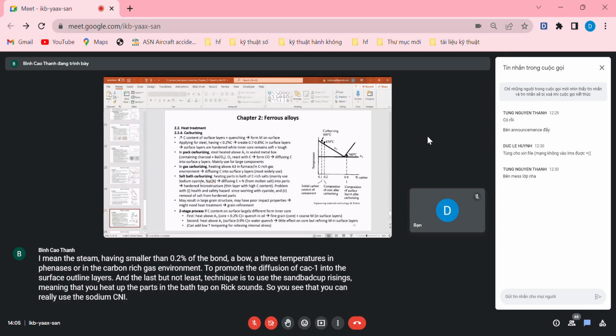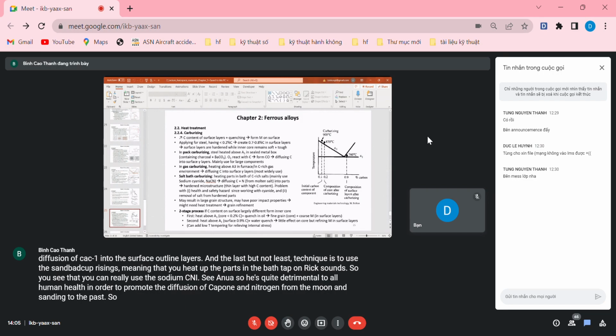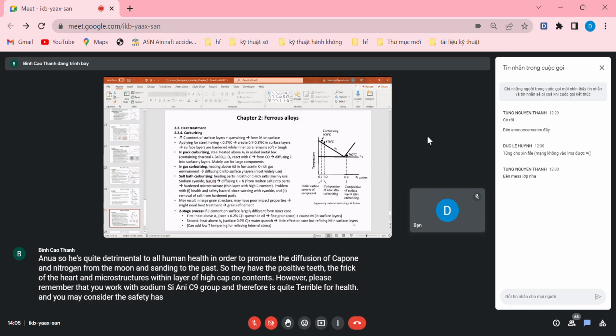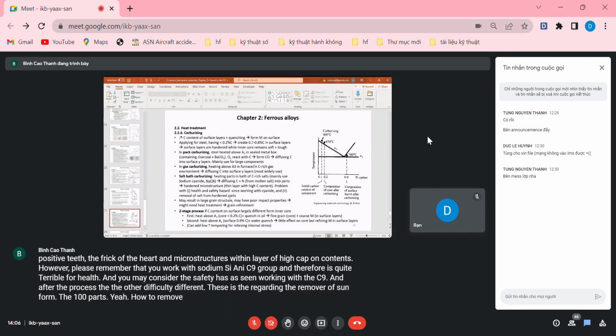You mainly use sodium cyanide, so it's quite detrimental to human health. It promotes the diffusion of carbon and nitrogen from the molten salt into the part, with the positive effect of a hardened microstructure with a thin layer of high carbon content. However, please remember that you work with sodium cyanide, which is quite terrible for health. You may consider the safety hazards in working with cyanide. After the process, another difficulty is the removal of salt from the hardened parts. How to remove the cyanide from the part is one of the issues you need to consider.